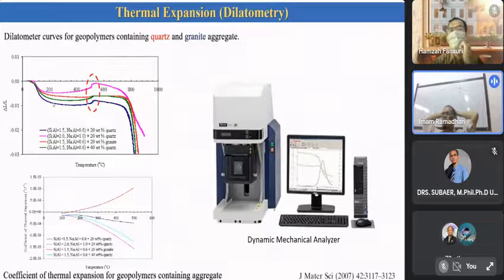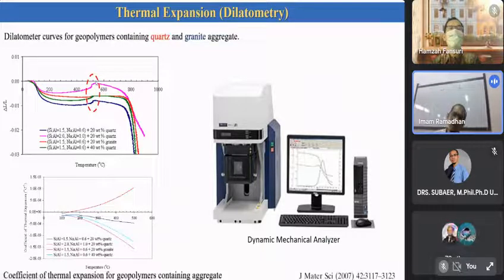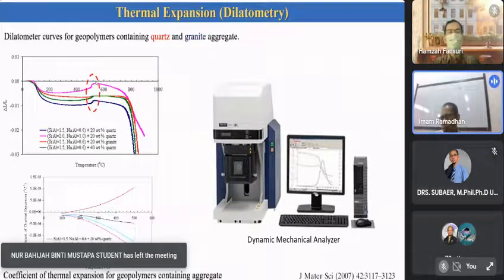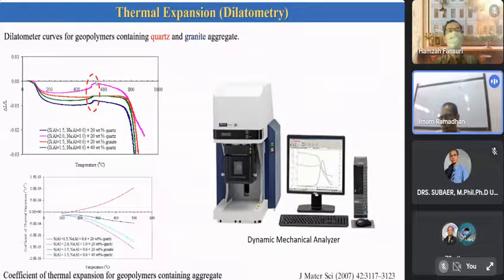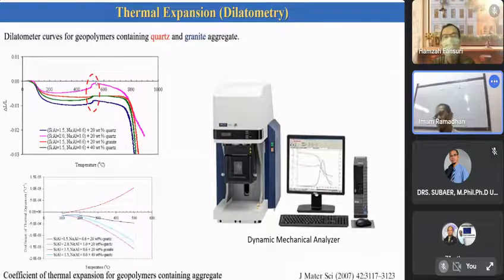It means that the geopolymer will solidify. The density becomes higher. You can see there is a kink around 500 degrees here. This is mainly caused by the aggregates. So if you put an aggregate inside the geopolymer, make sure that the aggregate you use is not one that has a high thermal expansion coefficient, because otherwise the material will get cracks, or the crack development will grow very fast at around 500 degrees Celsius, especially if you use quartz.